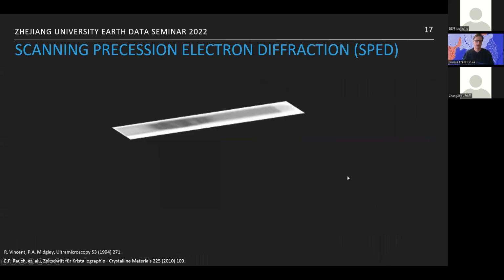The way this works is that we use a special type of diffraction technique, very similar to how you'd run a precession experiment in a synchrotron. But in an electron microscope, it's very hard for us to rock our sample through 360 degrees of rotation with respect to the beam. Instead, we can very easily rotate our beam with respect to the sample. We rock it above the sample, and then we do a counter rock underneath of it. What we're able to get are noise reduced diffraction patterns, and we're able to then scan that across the sample, as you saw in this little cartoon.